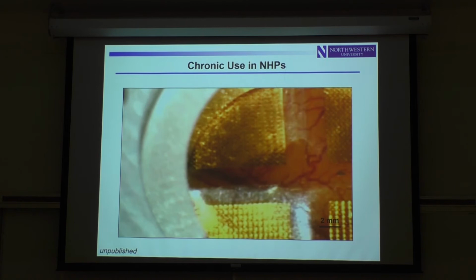So I should point out, we published a few papers. This was back in 2011. The biggest problem with these platforms is that it's very difficult to keep biofluids out of the biased electrical backplane. That's a key essential feature of these devices, because if biofluids penetrate in, then immediately you have a leakage path for current to flow into the surrounding tissue, which is a big problem. I won't go through it, but we spent almost half a decade working on materials that would allow almost perfectly impenetrable layers that would prevent biofluid ingress in that way. It turns out to be highly non-trivial, because you need to do that in submicron thick films. But you can, in fact, do it. We've done it. I won't tell you the details, but now we have deployments of devices in animal models that are providing stable functionality for more than a year now, and we're working on non-human primates as well. So that's kind of where this is going.